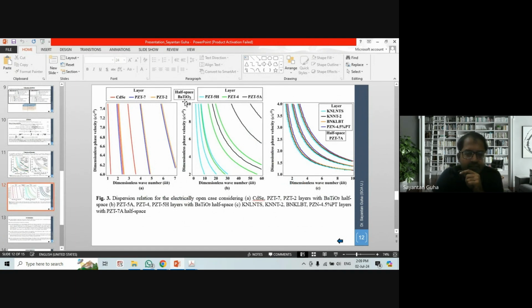Once again, I have composed a SAW device with a BaTiO3 half space followed by 6 different types of individual layers. And these 3 figures, A, B, and C, correspond to the electrically open case. For the first case, we see that for lower values of wave numbers, the phase velocity magnitude is the least for CdSe, followed by PZT7, followed by PZT2. So it can be seen that the phase velocity is least for CdSe.